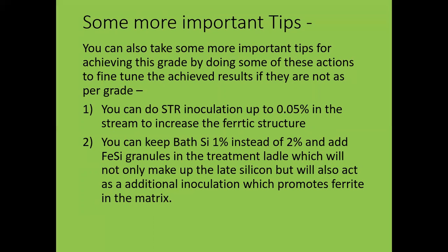desired properties. You can keep bath silicon 1% instead of 2% and add some ferrosilicon granules in the treatment ladle, which will not only make up the late silicon addition but also act as an additional inoculation, which promotes ferritic structure in the matrix. So, this is another important suggestion I'm giving. If you're not achieving these properties, you can reduce the silicon percentage in the bath and increase it during the treatment with granules in the treatment ladle so that some effect of late inoculation will get added to your metal, which will promote ferritic structure in the matrix and help you in getting desired results.